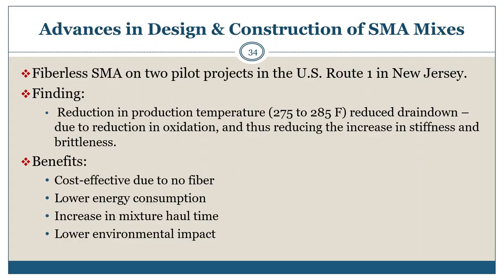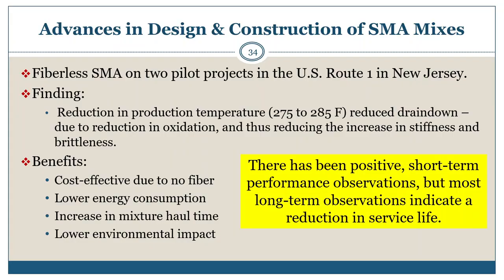Fiberless SMA mixtures have been placed on 2 pilot projects in the U.S., Route 1 in New Jersey. The finding from that study: there was a reduction in production temperature going to 275 to about 285 degrees Fahrenheit, which reduced drain down by not having fibers. There was also a reduction in oxidation by lower production temperatures, and thus reducing the increase in stiffness and brittleness as opposed to mixtures produced at higher temperatures. Some of the benefits are cost-effectiveness due to no fiber, low energy consumption, increase in haul time, and lower environmental impact.